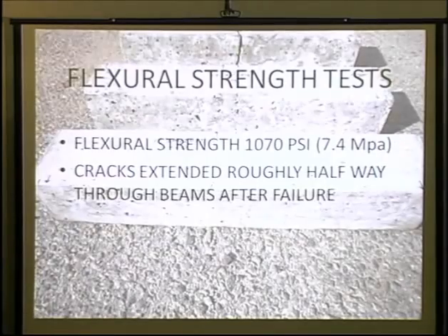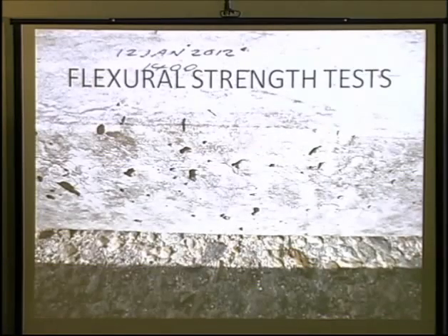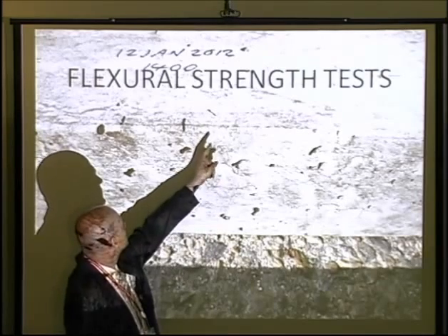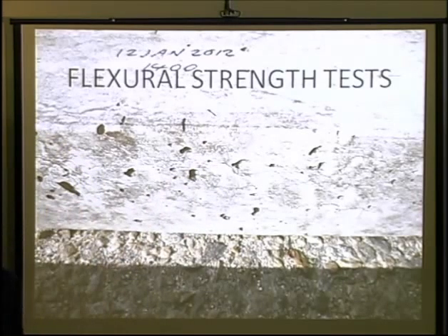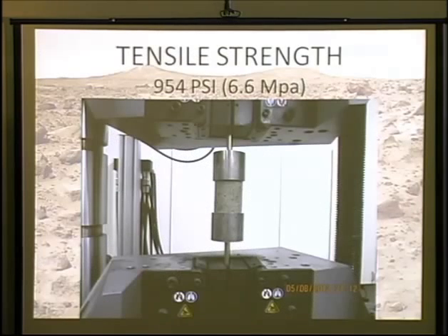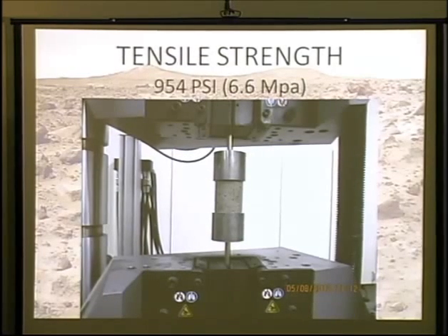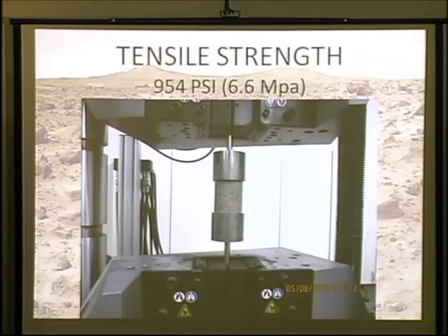These beams shown here are shown after failure, and you can just barely see there's a crack up the middle extending about halfway through the beam. After failure, there was still enough strength left in the beam to support my entire weight. So that's another big advantage of it. And I also did direct tensile testing, pulling a sample apart, and got very good and consistent tensile strength with it of nearly 1,000 pounds per square inch.